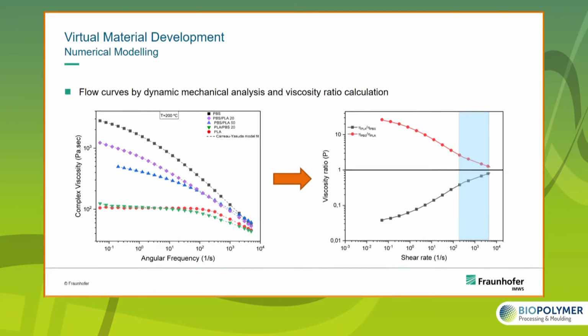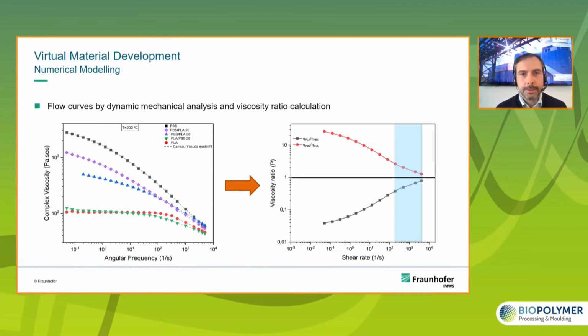And you see on the left diagram that we had much different rheological behavior of the two polymers. So the PBS had a much higher viscosity and a much more pronounced shear thinning effect of the flow. So a strong decrease of the viscosity with increasing shear rate, whereas the PLA is more or less constant in the flow behavior. We use these data to calculate the viscosity ratio of the two polymers, and this is shown on the right side. And here you can see that with increasing shear rate, the viscosity ratio comes close to 1. And if we remember one slide back, the particle breakup in this region of a viscosity ratio close to 1 is preferred in the necking